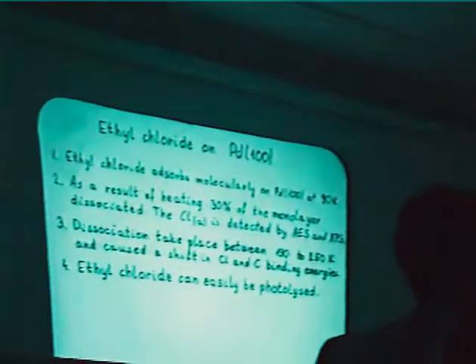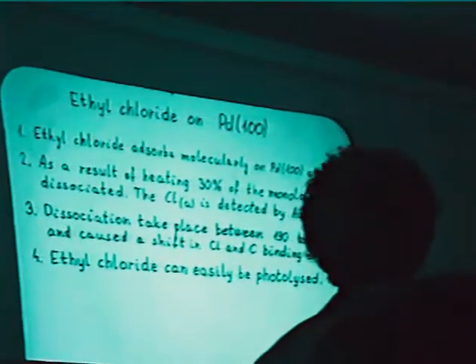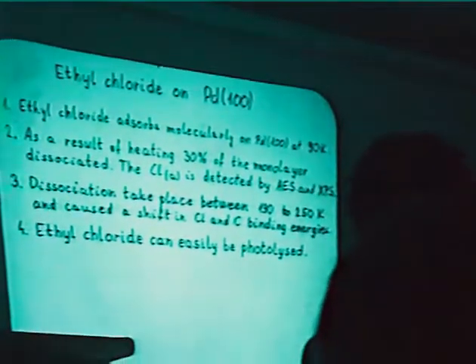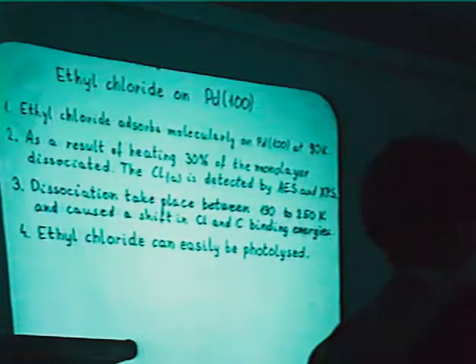The last topic is ethyl chloride adsorbed on the palladium surface. We can summarize the main effects. Ethyl chloride adsorbs molecularly at low temperatures. When we heated the adsorbed ethyl chloride to higher temperature,